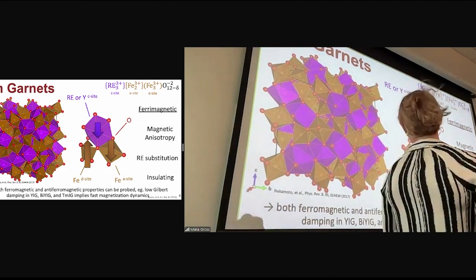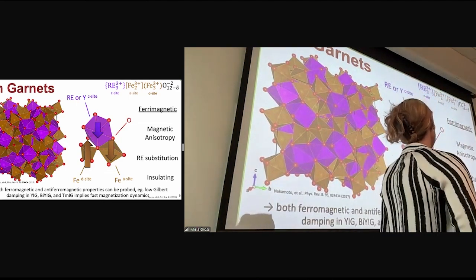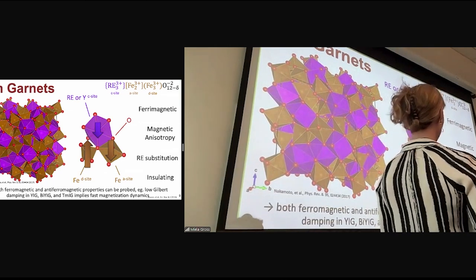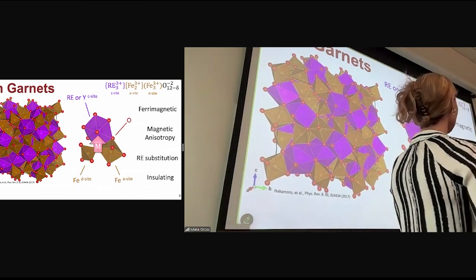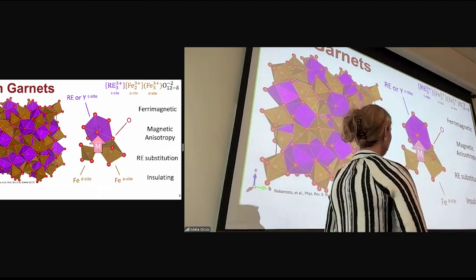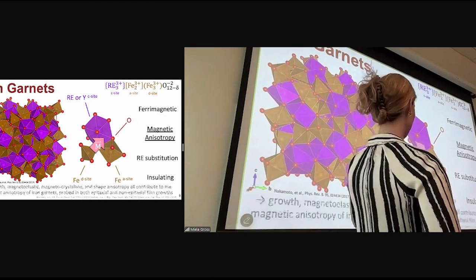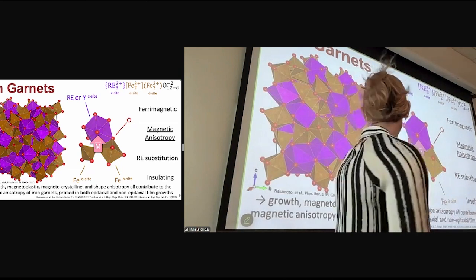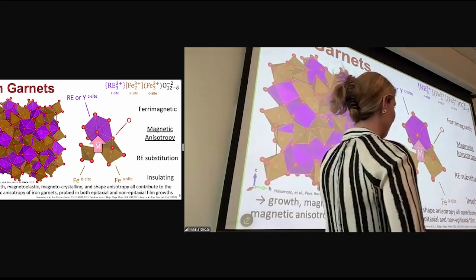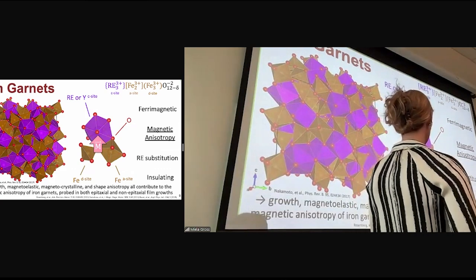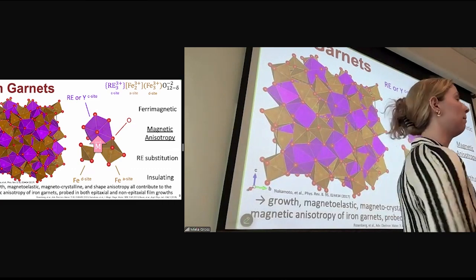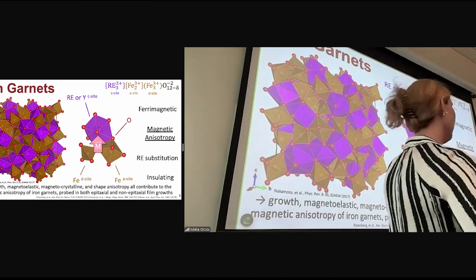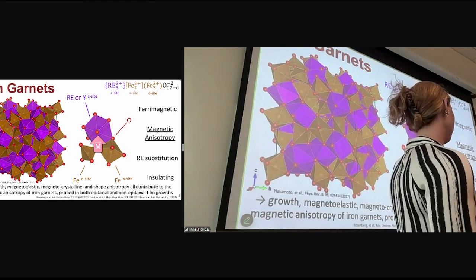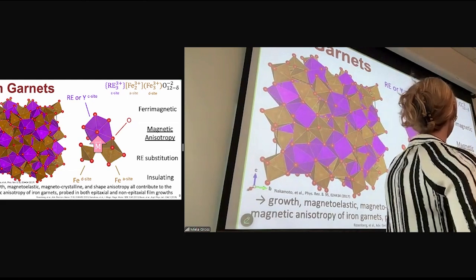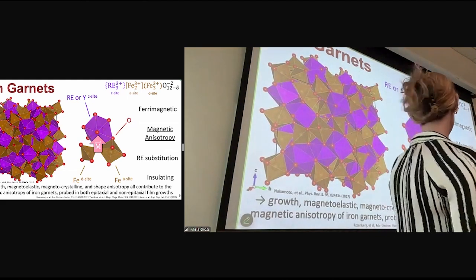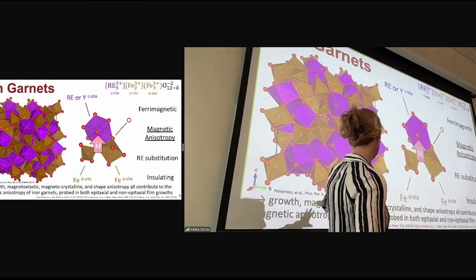For example, garnets have pretty low Gilbert damping, like I mentioned in the bismuth YIG and some other types of garnets, which allows for fast magnetization dynamics, but they still have a net magnetic moment like this that allows us to read out their magnetization. This net moment can be tuned to lie along a specific orientation, and that's called magnetic anisotropy. Growth, magnetoelastic, magnetocrystalline, and shape anisotropy all contribute to the net magnetic anisotropy of iron garnets. It allows us to achieve things like PMA, perpendicular magnetic anisotropy, in thin film garnets, and that can be probed in both epitaxial and non-epitaxial film growth. So like single crystal and polycrystal and stuff. Yeah, and that comes from a combination of strain and ion substitution, specifically in the magnetoelastic anisotropy.